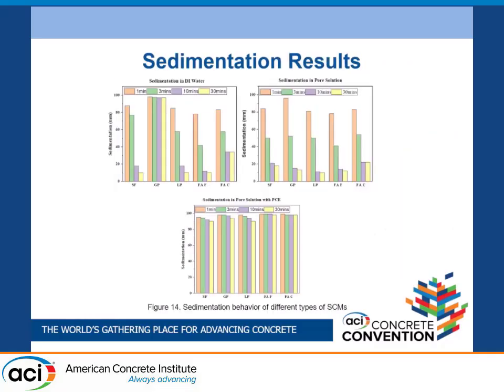Next is the sedimentation test results. We performed sedimentation tests in DI water, in pore solution, and in pore solution with polycarboxylate ether (PCE), at different times. We can clearly see that glass powder is very stable in DI water, but in pore solution, the glass powder has a rapid rate of sedimentation. The other SCMs show almost the same behavior in DI water and pore solution, indicating they are agglomerating in all the solutions.